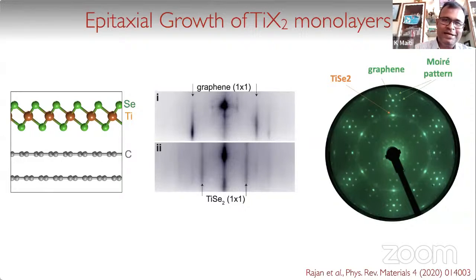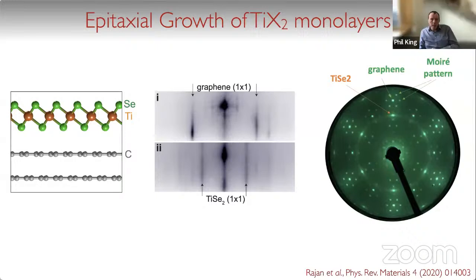Is there any idea behind using graphene instead of some other substrate? Really it's a bit of a Goldilocks substrate, I would say, for these 2D materials, in that the interaction between the graphene and the epilayer is sufficiently weak that you're growing fully relaxed. And so it's almost a freestanding monolayer, but there's still just enough of an interaction that you get an epitaxial alignment between the two.